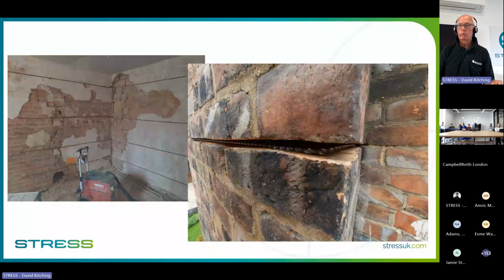So the important thing is to remove the depth you need to. If you're going in with a single bar, it'll probably be at least 20 millimeters into the bed joint, and make sure you've removed brick to brick, so you are actually going to bond to the brick. You then vacuum out that slot, you wash it out, you prime it, you put your first bead of grout in, pop the bar in, and then grout over the top, leaving 15 millimeters back for the pointing that goes on the top. Again, you've probably seen these guys a number of times, 5 millimeters of repointing over the top. Of course, what happens within a couple of years, it starts falling out. You need it 2 to 1, basically. So it's a 10 mil joint.